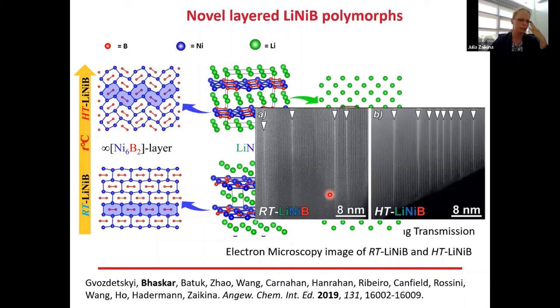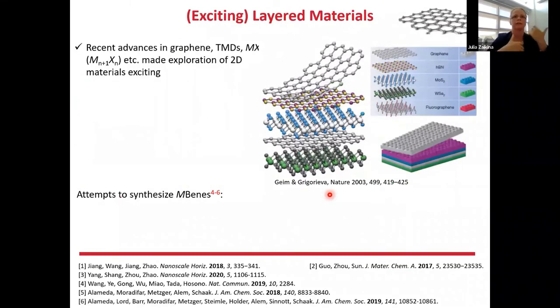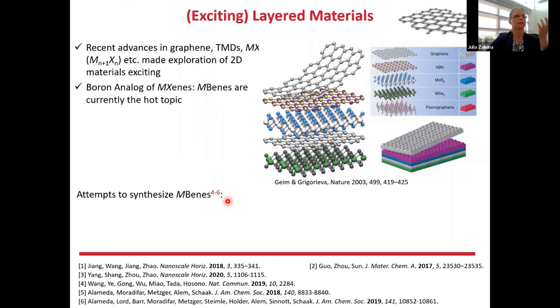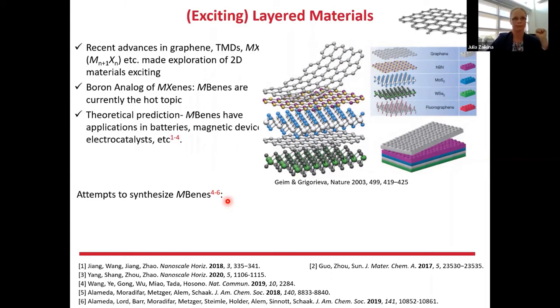And an additional reason why we were very excited about the discovery of these layered compounds is that, well, I guess you all are aware of the rise of graphene as a single layer of carbon, as well as many other two-dimensional materials among the nitrides, sulfides. And so if you want to target the borides, typically we don't have a good precursor. And our discovered lithium-nickel boride is one of the possible precursors to synthesize two-dimensional borides called MBenes.